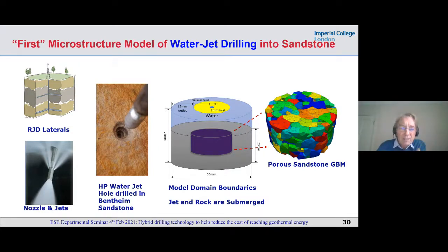So for example, this is like a cylinder of rock in gray. The solid domain is in gray, but the fluid domain is shown in blue above, and that would be static water in the first instance, sitting on top of solid rock. But there's a 2 millimeter inlet where we have this extremely high velocity water coming in at maximum 300 meters per second, and that is what we can use to break the rock. You can see on the right hand side a microstructure model of that granular system that we're going to put in the middle there in that purple area.